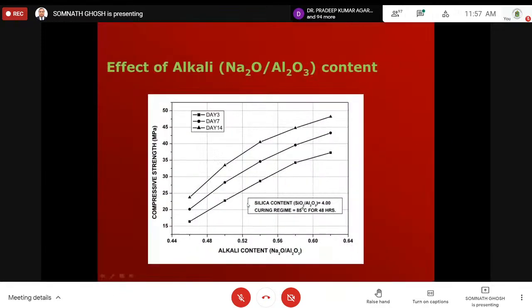We don't have time to discuss all these things in detail. Now you see, alkali content is basically expressed in terms of this ratio. 85 degree temperature we found best, for 48 hours. Silica content 4%, which means this ratio is 4. Then if you change it, the compressive strength is increasing. See, there's 7. Whatever result I have shown you in the graph earlier, it has gone up to 50, very close to 50.